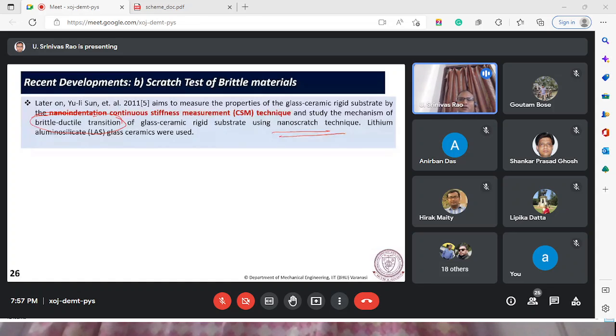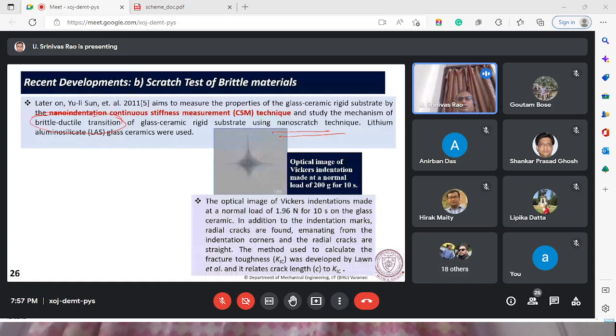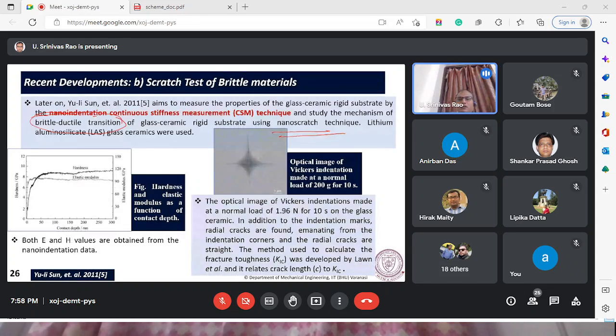And then the indentation technique is another technique, this one, the Vickers indentation technique. Normally, what we expect in a hardness test is this impression on the specimen, and then we have those diagonals measured. What we don't want is these things. These are not required.